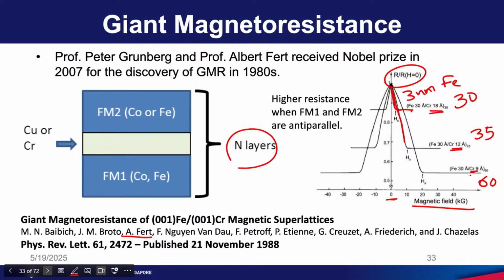For the second set, the resistance goes to this value. For the third set, where we have 60 bilayers, the resistance drops to an even larger value. If you look at this difference, this is almost like a 100% change. The change in the resistance as a function of magnetic field is around 100%. So, this value is very large.